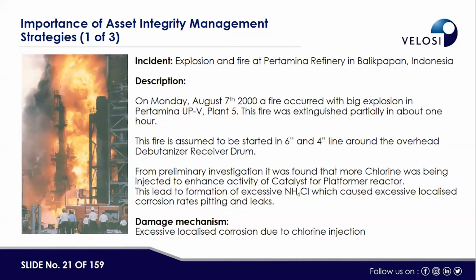In the preliminary investigation, it was found that more chlorine was being injected to enhance activity of the catalyst for the platformer reactor. This led to formation of excessive ammonium chloride, which caused excessive localized corrosion rates, pitting, and leaks. The main cause was excessive localized corrosion due to chlorine injection.